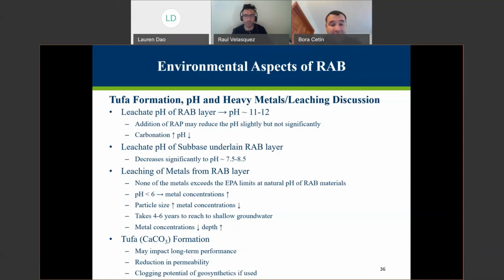And if the RAP pH, not the sub-base or clay pH, goes below 6, then yes, you start seeing a significant amount of metal concentrations increasing, but it is very unlikely that this scenario will happen. There is no acid rain that will leach through a concrete or asphalt surface to the base layer and cause a significant pH drop in the base layers. And to minimize the metal concentration, large-sized particle RCAs can be used. Multiple studies showed that if you use coarser materials, they tend to leach less because of the lower surface area of these materials.